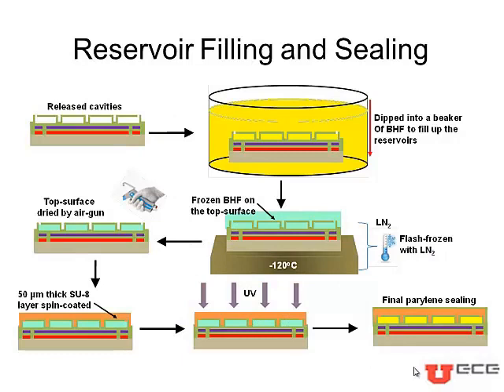This slide discusses in detail the cavity filling and sealing process. First, the sample with released hollow cavities is dipped into a bath of BHF. Next, it is pulled out of the bath and immediately flash frozen by placing it on a liquid nitrogen cooled metal chuck. This freezes the BHF inside the reservoir and also leaves a thin film of frozen BHF on the surface of the reservoir. The frozen BHF on the top surface of the reservoir can be removed by air drying using an air gun for about 1 minute. This leaves the top surface cold but dry.